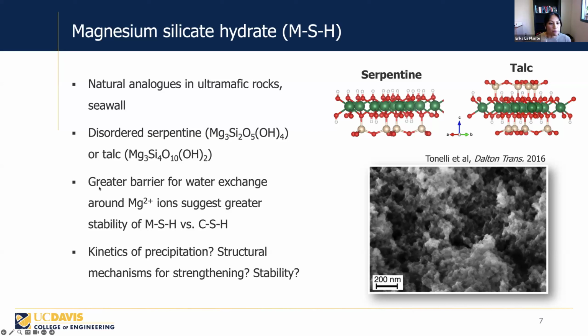The hypothesis around the use of MSH is the characteristic of the magnesium ions compared to the calcium ions. Because of the greater barrier for water exchange around the magnesium ions, this suggests the greater stability of MSH cements compared to CSH cements. And that would also be consistent with the greater degree of silicate polymerization in MSH, where we have sheets instead of chains, as what we see for CSH. This is a micrograph here showing what an MSH might look like, and so it's showing these opportunities.